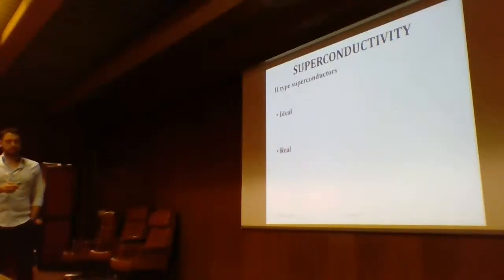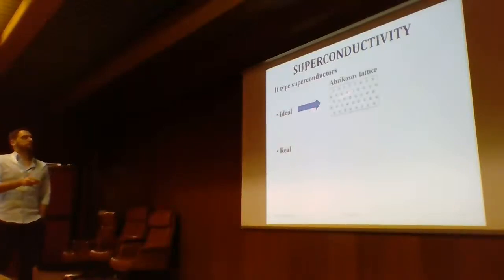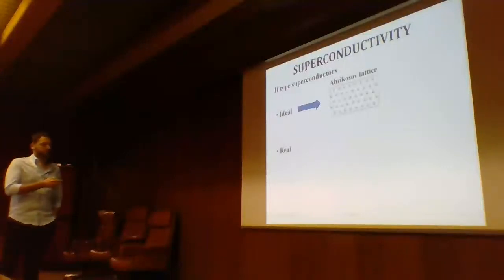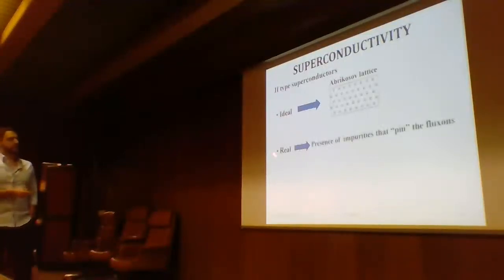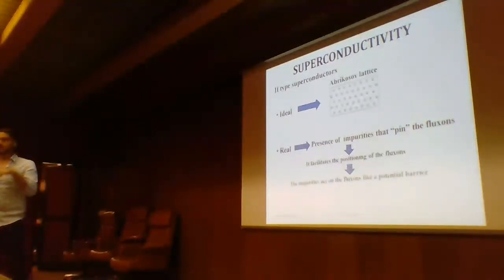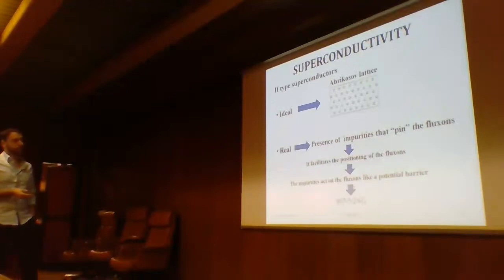In general, for the second type of superconductor, we can say there is an ideal case and a real case. The ideal case is characterized by the arrangement of the vortices in a so-called Abrikosov lattice, that is a very regular vortex lattice. But as you know, usually we are never in the ideal case. The real case is characterized by the presence of impurities that pin the vortices that have penetrated your material. This presence of impurities facilitates the positioning of the fluxons inside your material, and the impurities act on the fluxons like a potential barrier. This kind of phenomenon is very important in superconductivity, and it is called the pinning phenomenon.